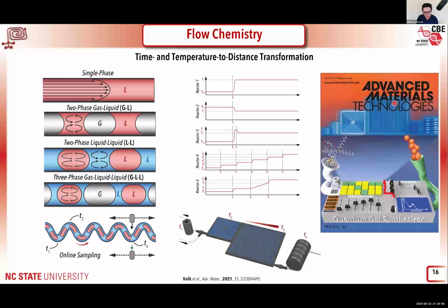Now let's start with reaction miniaturization, the importance of flow reactors. The other reason that we prefer to use flow reactors over batch reactors for synthesizing materials is its unique characteristic of time and temperature to distance transformation. When you run a reaction in an autoclave or a batch reactor, time means just waiting for a different amount of time in your reactor. But when you're running a reaction in a flow reactor, time actually means different positions along your reactor. This is the time to distance transformation. By controlling the speed of these droplets moving along the reactor, you can have different reaction times along your reactor. And you can have different types of flow formats to run your reactions. You can have just all liquid, you can do gas liquid, liquid, and so on.